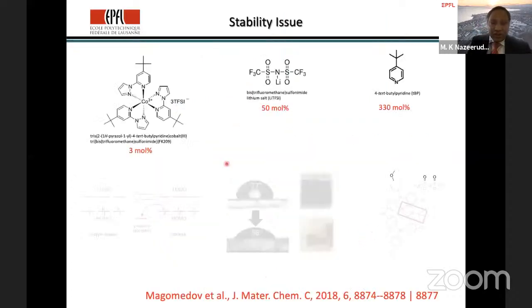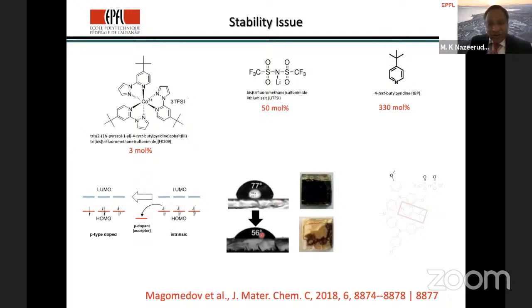The reason why this spiro has issues is that it is not highly mobile or conductive. So we have to dope it with dopants. One of the dopants is the cobalt-3 complex, shown on the left side, lithium TFSI, and tertiary butyl pyridine. By doping with these agents, you oxidize the intrinsic hole transporting material, and by oxidizing it, you increase the mobility. That enhances your hygroscopicity, as shown here. Look at spiro-OMeTAD without any dopants and with the dopants: the contact angle decreases significantly.